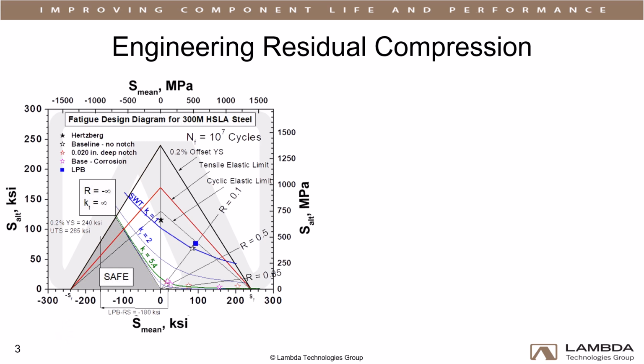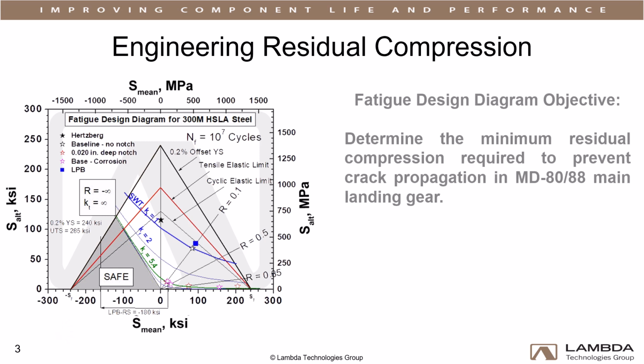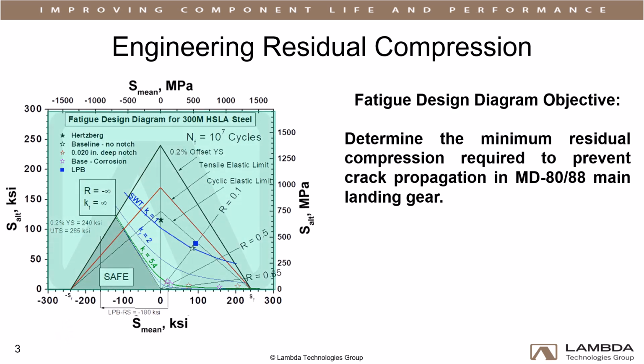This process begins with calculating the minimum residual stress required to mitigate fatigue and stress corrosion cracking. We do this using our proprietary fatigue design diagram. Knowing the mean and alternating service stresses, we can determine the amount of compression needed to provide damage tolerance sufficient to avoid failure for the component design life. This is indicated by the triangular region marked safe in the diagram.